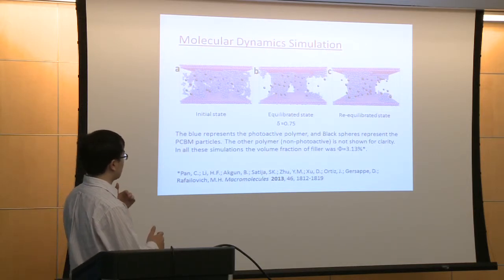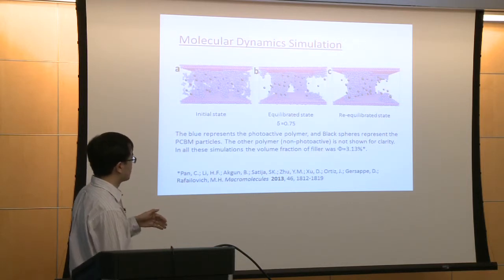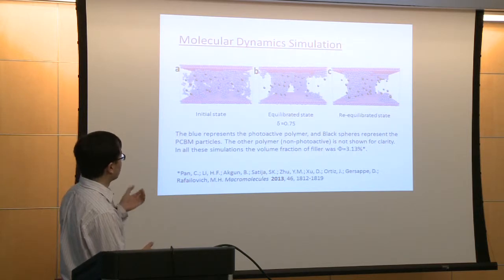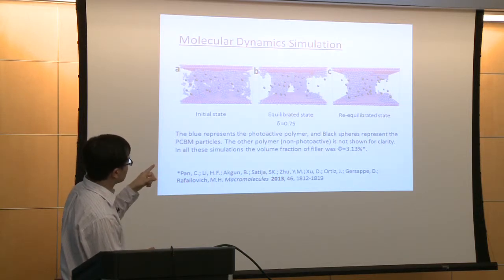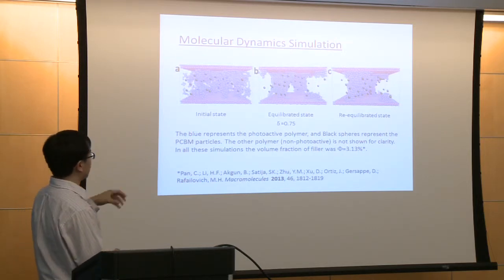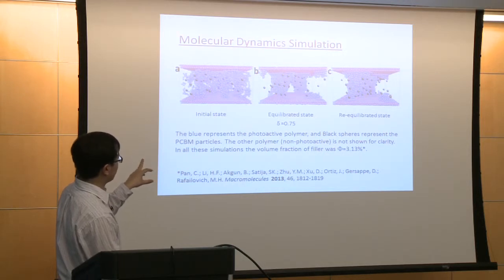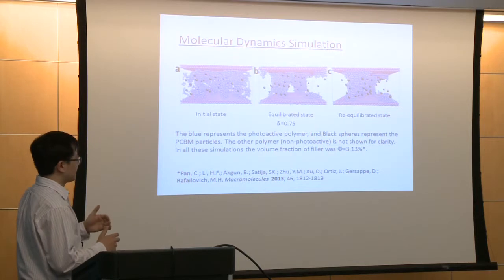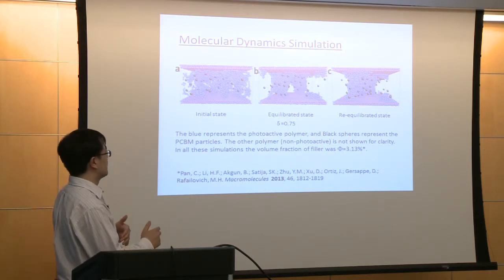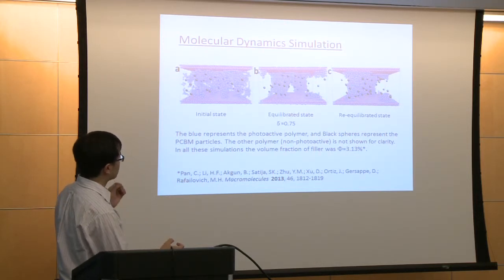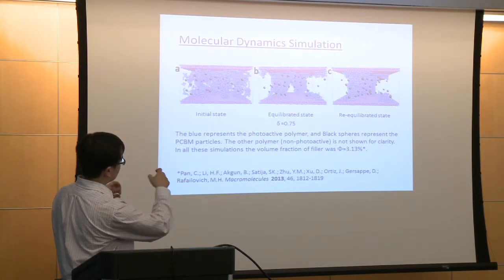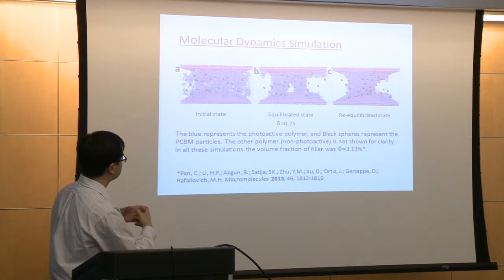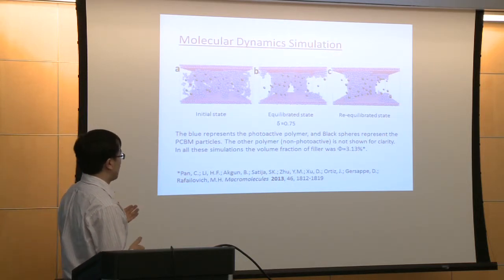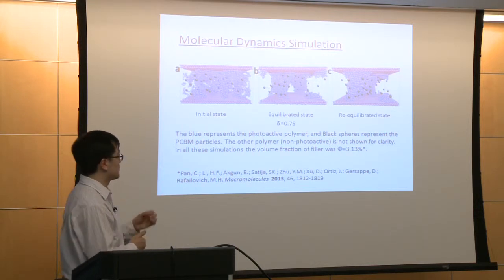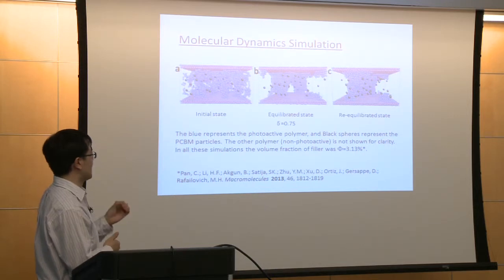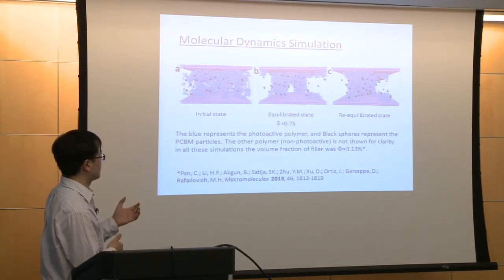You cannot see any specific structure within the area. However, if you continue to run the program, which in the experiment means we anneal the system at a certain temperature, you can clearly see the column structure already formed within the active layer, and you can see PCBM kind of segregate at the interface, but it doesn't matter. If you continue running the program, which means you re-equilibrate the system, you will see a very interesting thing: the 2 columns from the second picture merge together to form 1 column. So what this simulation can tell us is basically if we experimentally choose a proper temperature and the proper annealing time, we can certainly achieve the column structure within the active layer.